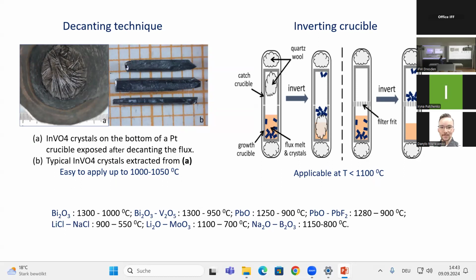It is doable up to 1000 degrees, as shown in this photo. You get InVO4 crystals on the crucible bottom. It's indium vanadium oxide grown in our group. And this is the basic idea for any other approach, because you can do this decanting inside a hot furnace, although it requires a more complicated experimental setup. And here is a list of the most powerful, famous, and well-known fluxes, like bismuth oxide, lead oxide, and several more. But the list is not complete, because we know tens and tens of different fluxes, and hundreds or even thousands of materials were grown by flux.